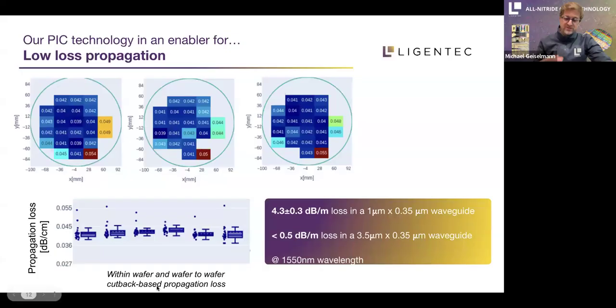cutback based propagation loss. So you have different spirals of different lengths, and then retrieve from that measurement the propagation loss in such a waveguide structure. And here we have to distinguish the geometry of the waveguide structure, which is very important if we talk about propagation losses. We have a 1 micron by 350 nanometer waveguide where we get around 4 dB per meter propagation loss. And if we make the waveguide wider in a straight section, then we can get even below, actually it's 0.2 dB per meter propagation loss that we can get in a wide waveguide at 1550 nanometer wavelength.